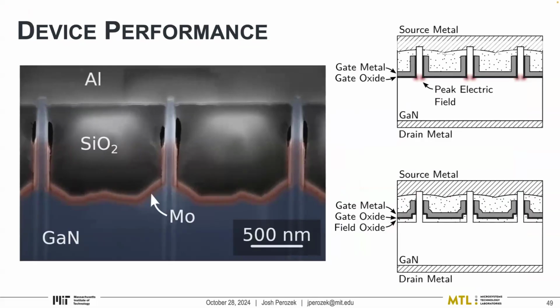We kept it conservative, and what we didn't include was what we call the field oxide. That was that first step in the last process flow I showed you. The importance of that is that at the base of these fins, you have a sharp corner for your gate. And corners are really bad for any semiconductor device. It amplifies your electric field and tends to break whatever's there.